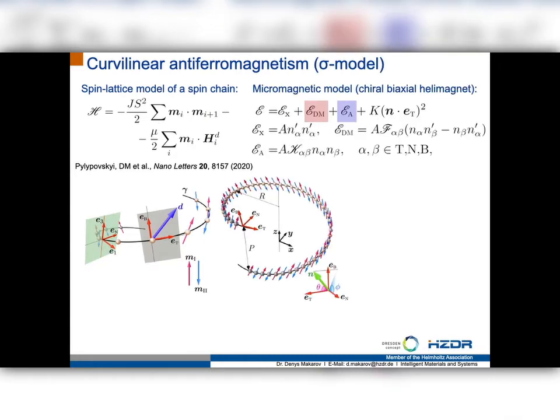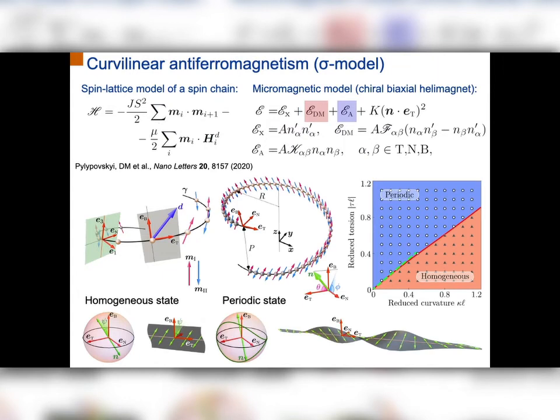In this case, you can transform the spin lattice model into a micromagnetic model, where you will have from dipole-dipole interaction hard axis anisotropy along the tangential direction, and you will have the terms which we already discussed before in exchange energy, which are anisotropy, which comes from restructuring the exchange, and Dzyaloshinskii-Moriya interaction. As soon as you have Dzyaloshinskii-Moriya interaction in the system, this and anisotropy make your achiral isotropic antiferromagnet behave as a chiral biaxial helimagnet with a geometry-driven phase transition, a helimagnetic phase transition between periodic and homogeneous states.